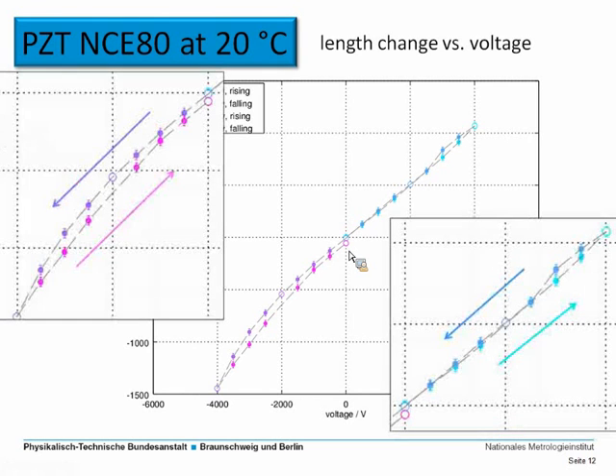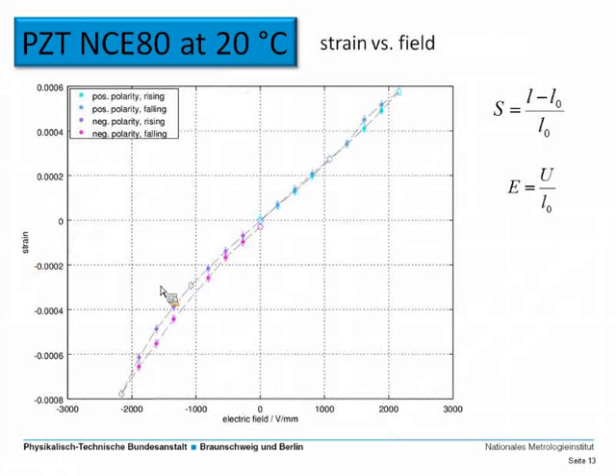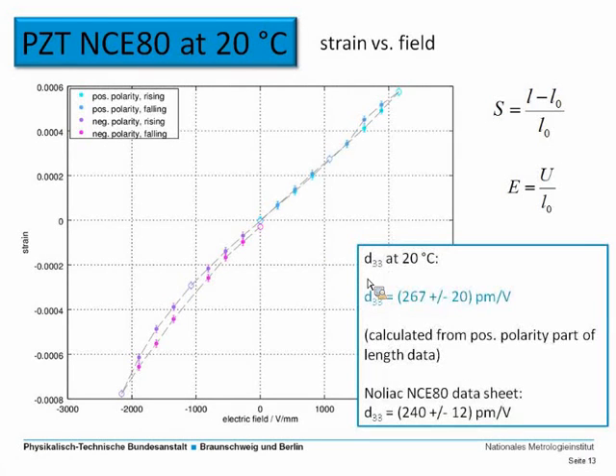So just to zoom in so that you can see what it looks like, and especially for the negative polarity part here, you can see that there is some kind of hysteresis behavior. This is again the same information, just plotted a little bit differently. If you're more familiar with this kind of representation, this is the strain shown as a function of the electric field. So strain and field are defined like this. It's the same information as before. And from these data, you can calculate the D33, which is just a rough estimation for the moment, and we get a value of roughly 270 picometers per volt, which agrees very nicely with the data provided by Noliac. So this is encouraging for some first results.